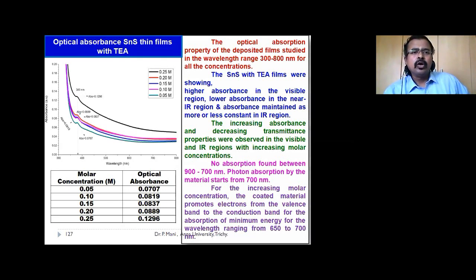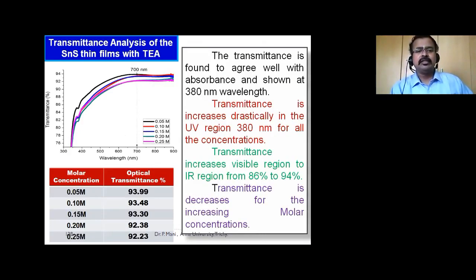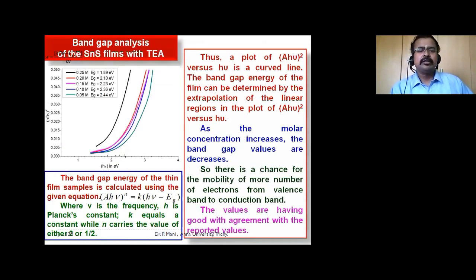Then optical absorbance of tin sulfide thin films with the TEA. It ranges between 0.1 to 0.08. Optical transmittance ranges from 92.23 to 93.99. Then band gap analysis. It ranges between 1.89 to 2.44 electron volts.